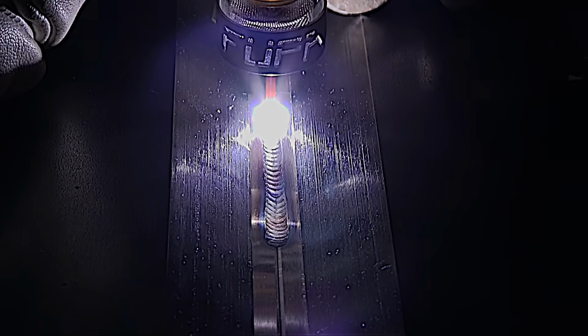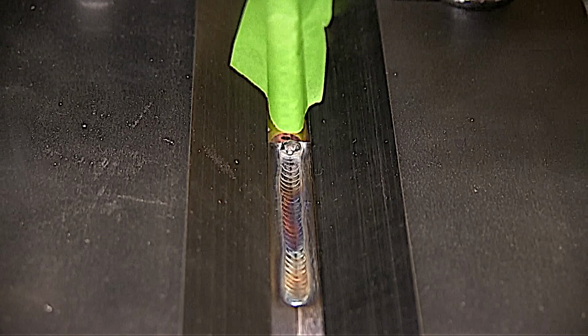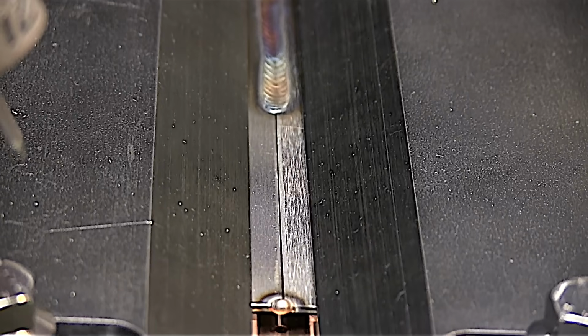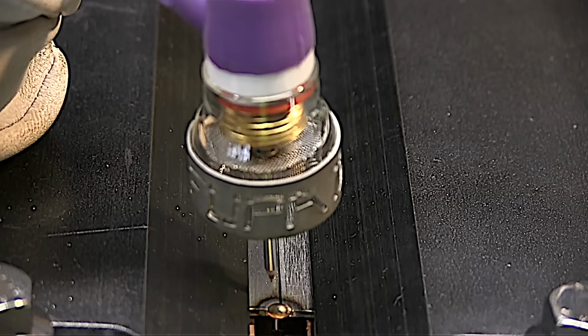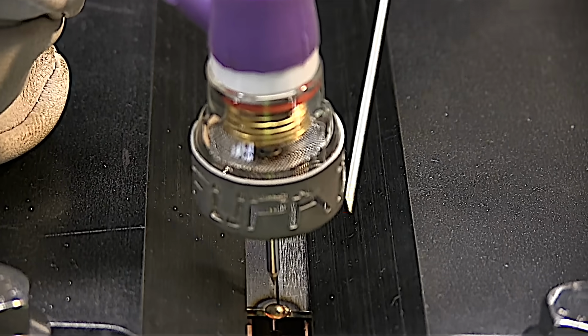Coming up to a tack, about 2 or 3 dabs before you get to the end tack, you've got to really start paying attention. You don't want to blow that end away. So right about here, I start letting off that pedal and really paying attention to the front of that puddle as it washes into that tack, and I'm getting off the amperage and trailing out to not leave a crater.